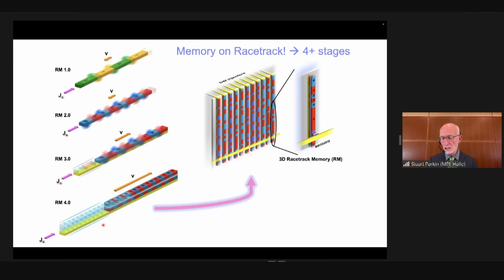This racetrack, as I briefly mentioned earlier, we have to avoid all the magnetic stray fields emanating from the domain walls, just as they emanate from the transitions between magnetic regions in a magnetic disk drive, allowing them to be detected by a spin valve sensor. Here we want to eliminate all these stray magnetic fields, otherwise they will cause interactions between neighboring domain walls in a single racetrack or between neighboring racetracks, which would have to be packed closely together to build a memory device that could have the capacity of a magnetic disk drive.